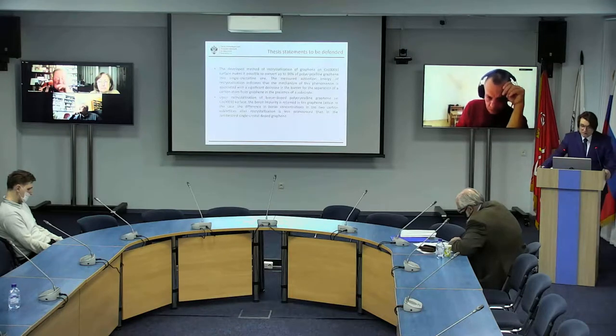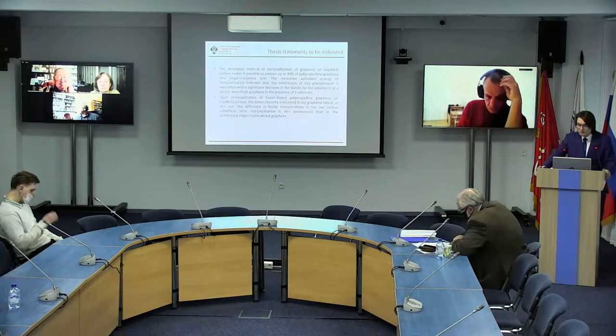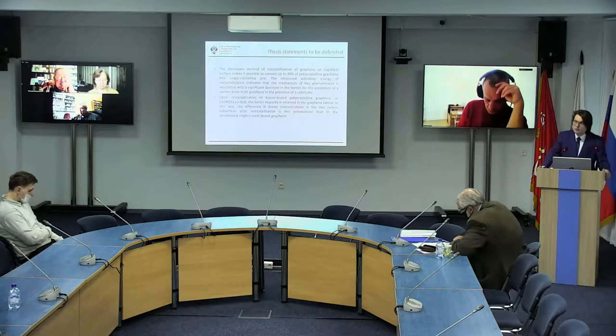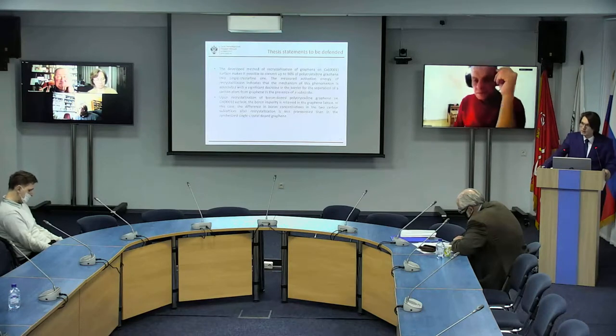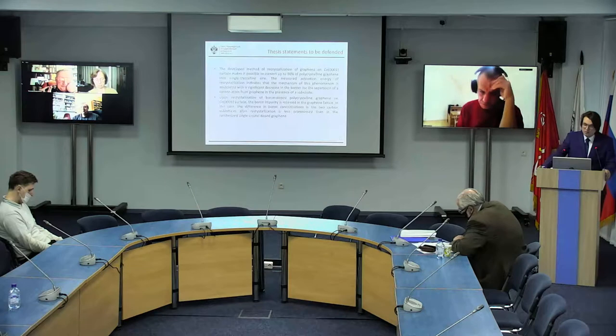And upon recrystallization of boron-doped polycrystalline graphene on cobalt surface, the boron impurity is retained in the graphene lattice. In this case, the difference in boron concentrations in the two carbon sublattices after recrystallization is less pronounced than in the synthesized single crystal doped graphene.